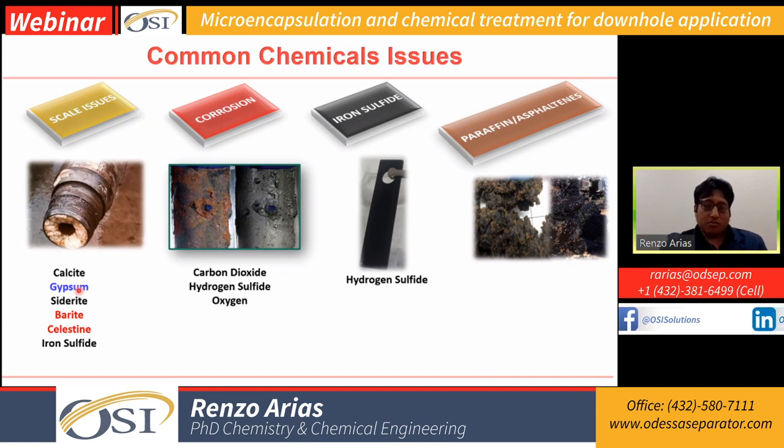In the case of the gypsum, which is the calcium sulfate, then that's different. It's not acid soluble. In this case, you need to transform this gypsum to a soluble salt that you can treat. So maybe you would use sodium hydroxide or any other base to change the solubility properties of this one. So still you can deal with that.